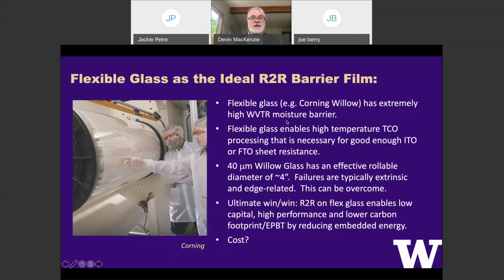Of course, an extremely high water vapor transmission rate barrier. Permeability of water is extraordinarily low. It's really not measurable. There's really not a technique that can measure how low it is coming out of glass or, say, thick metal foil or something like that. It's many orders of magnitude lower than the best we can measure, which is about 10 to the minus 6, 10 to the minus 7 grams per meter squared per day.